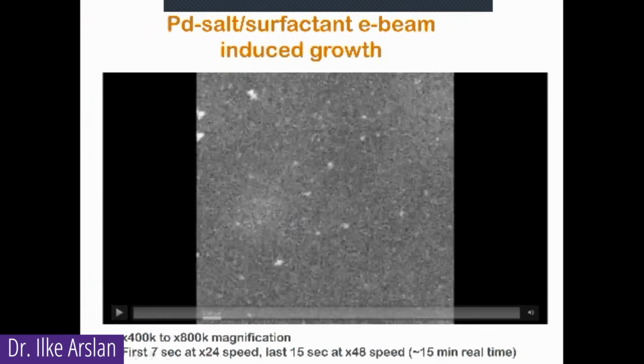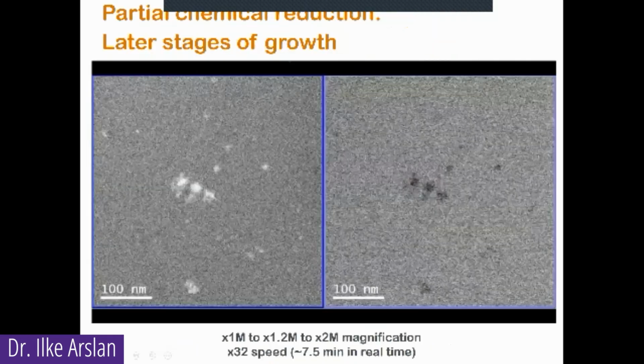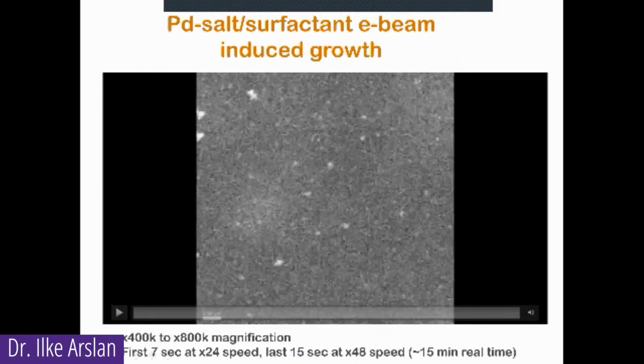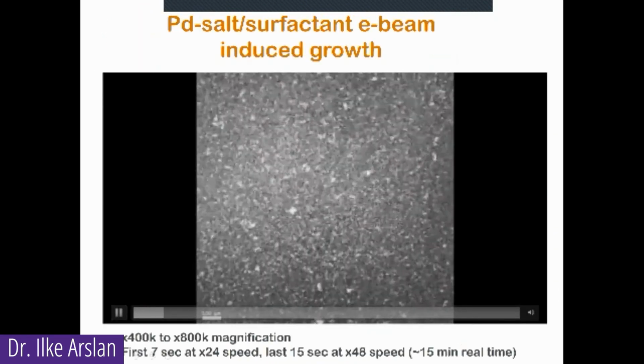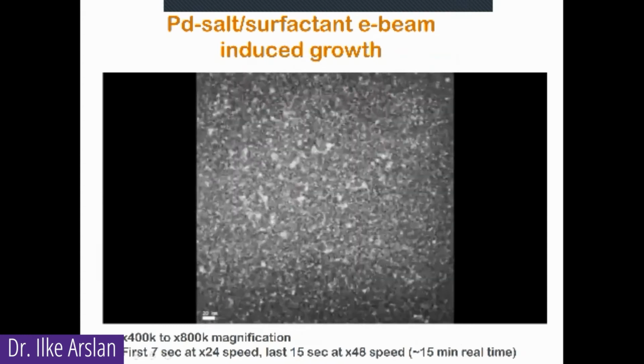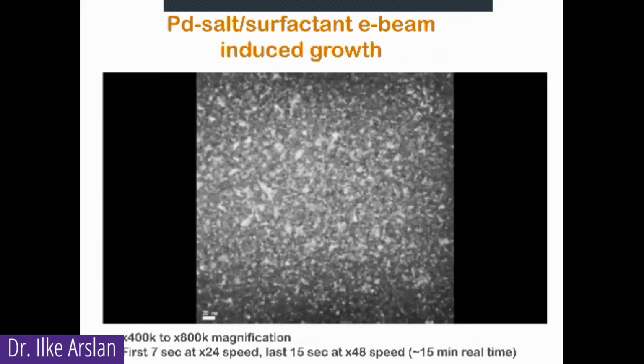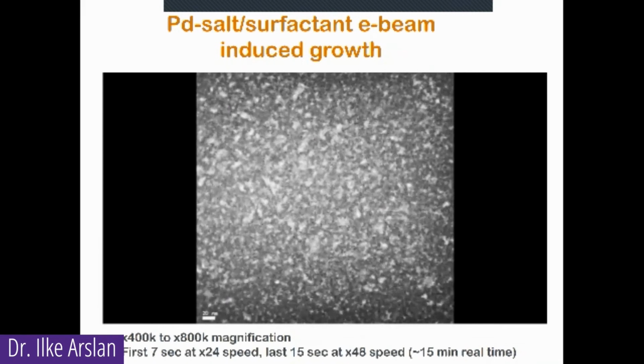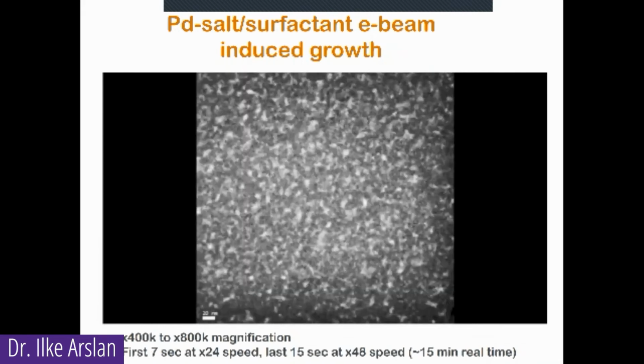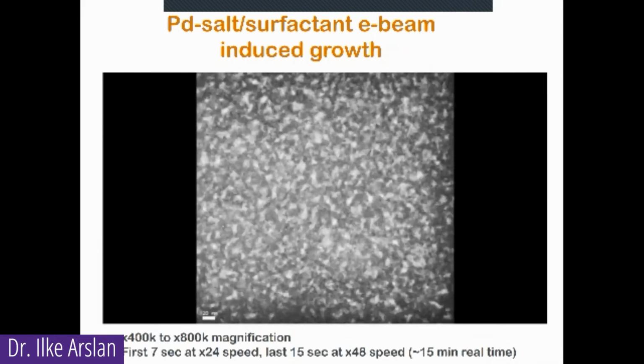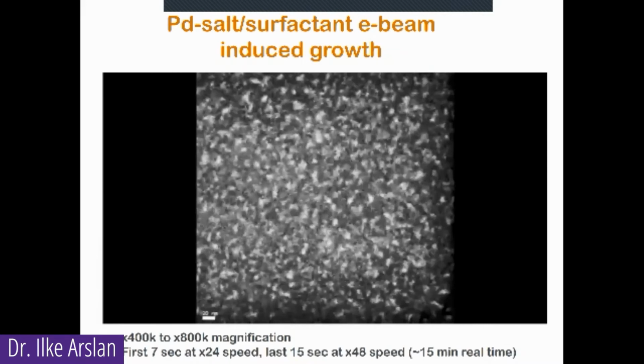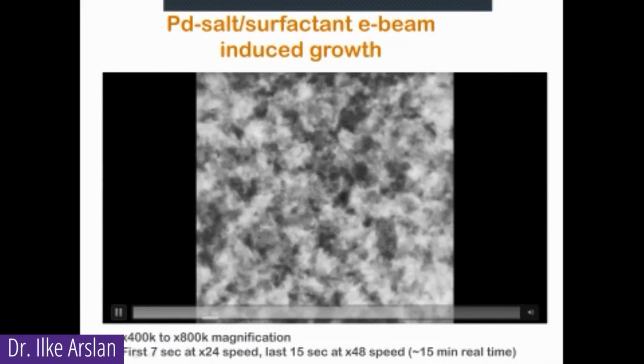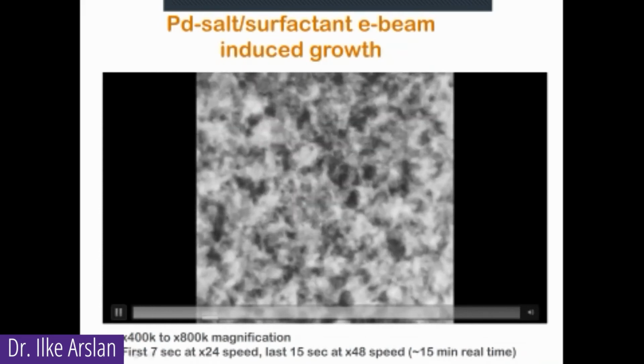Now, if we look at the surfactant with the electron beam induced growth, okay, here we go. You'll see that the bright areas again are the palladium, and they are reaching out towards each other to form pores around the surfactant. We can't see the surfactant, but we know that they're there because they're reaching out and forming these like wires around the pores to try to reach one another.